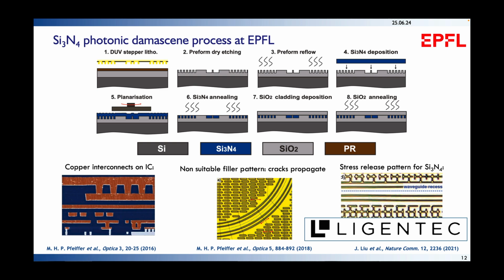And glass we can etch very well, it's a very well established chemistry to do that. And so what we do next is we fill those trenches with silicon nitride and also the stressor layer. And then we polish it. And that technique actually is known in the semiconductor industry. It's called copper damascene process.